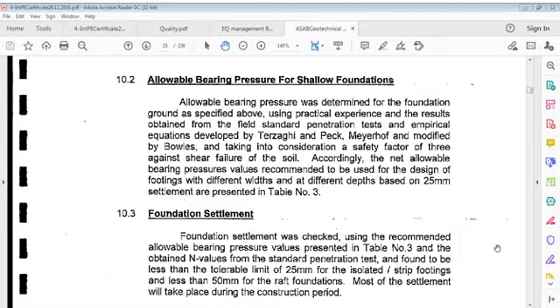Allowable bearing pressure was determined for foundation ground as specified above using practical experience and results obtained from field standard penetration tests and empirical equations developed by Terzaghi and Peck, and modified by Bowles, taking into consideration a safety factor of 3 against shear failure of soil. Accordingly, net allowable bearing pressure values are recommended to be used for design of footings with different widths and at different depths based on 25 mm settlement.